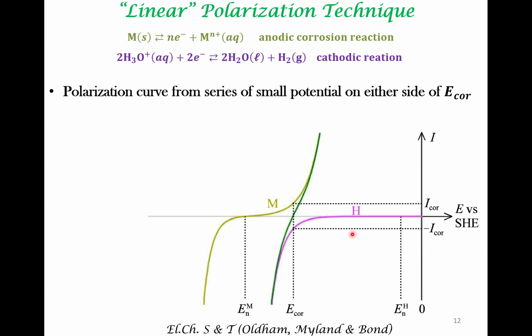Let's move on. There is another kind of experimental measurement, which is often referred to as the linear polarization technique. So what do we do? Here, this dark green curve is obtained via a series of potential changes on either side of E corrosion. Once this potential is established, you do a measurement corresponding to either side of E corrosion and get this green curve. Why is it called linear? Because very close to E corrosion, this curve, which is nonlinear, is expected to be linear. Because of this reason, it is called the linear polarization technique.